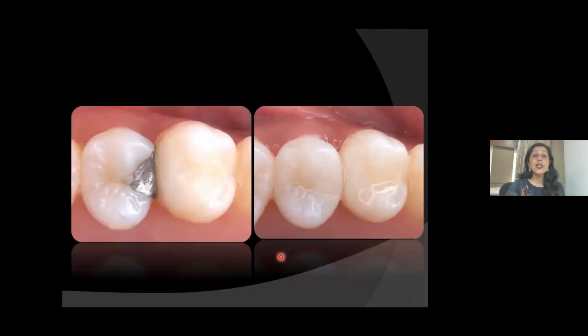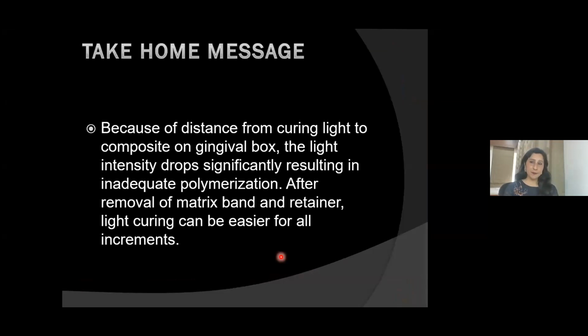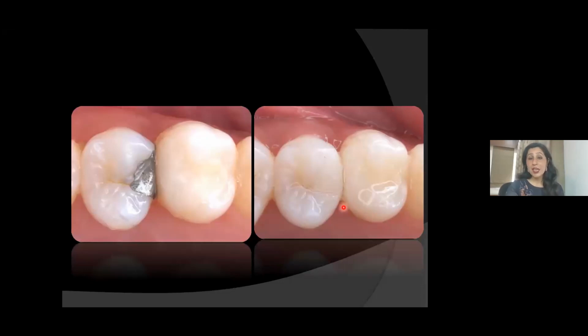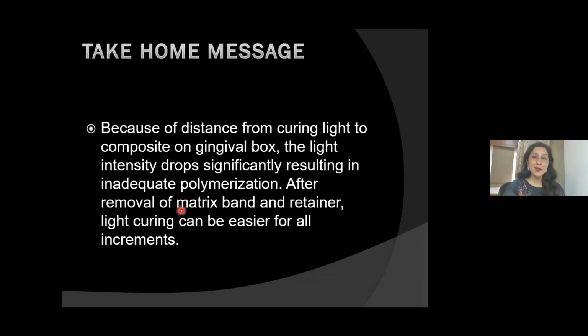And see, after finishing and polishing, this centripetal technique is done with vertical incremental layering. Because of the distance from the curing light to the composite on the gingival box, the light intensity drops significantly, resulting in inadequate polymerization. After removal of the matrix band and retainer, light curing can be easier for all increments. And this is what I was talking about: take your light cure probe to all the areas and light cure it, so that the intensity does not fall as it does from the top. The light intensity drops as the depth increases. So if you take your light here and here, your free radical generation can be more complete. It can never be complete, but it can definitely be enhanced.